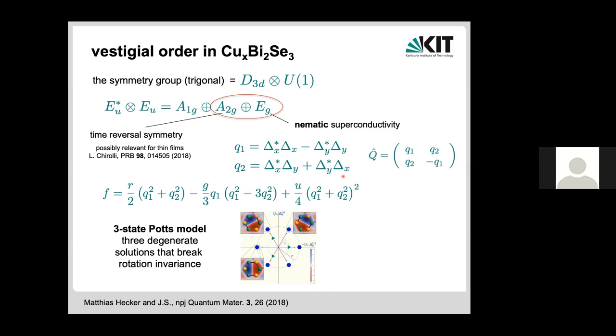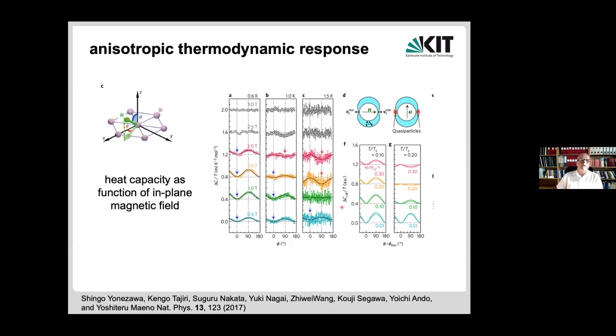Just interrupt for a second. The thing that I'm not quite sure about is that the currents are really governed by the phase stiffness, right? And I guess that in order to decide about the anisotropy you pick up in conductivity, it has to be that the phase stiffness is anisotropic. Is that completely obvious, how it works in this? Oh, it's much more trivial. You're actually breaking a symmetry. So if I go back, for a trigonal system, you would have, say, the resistivity along this direction and along the y direction actually be the same. But now we talk about...